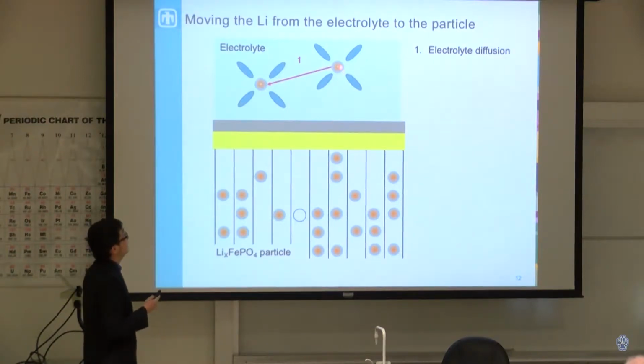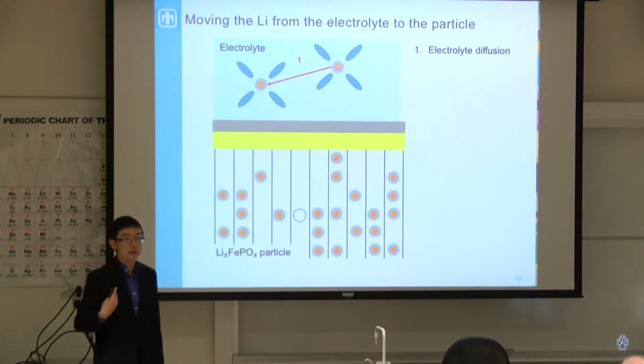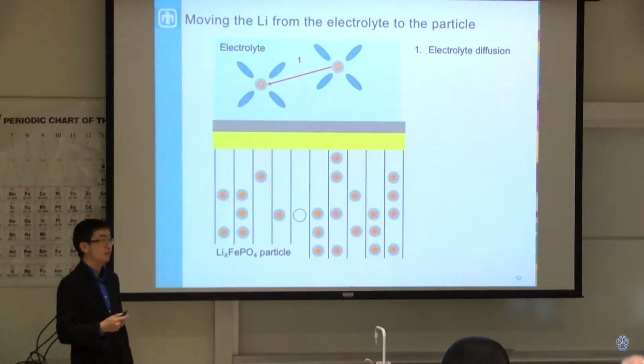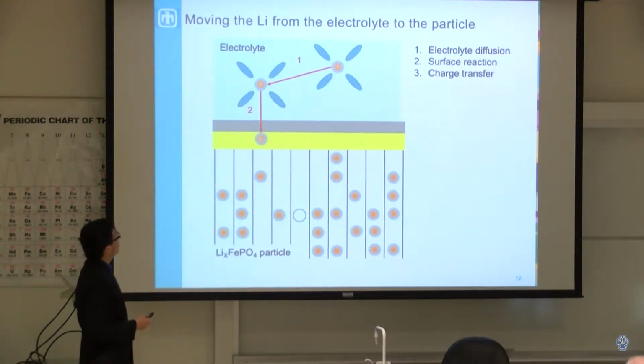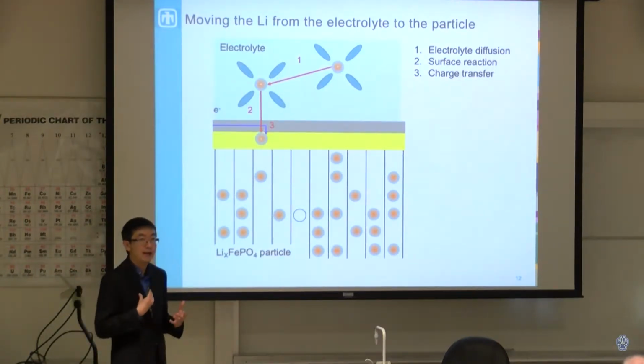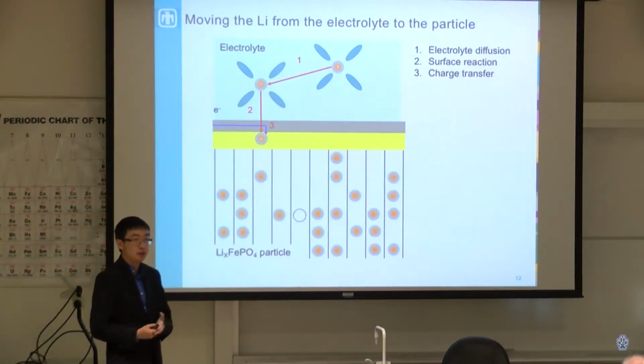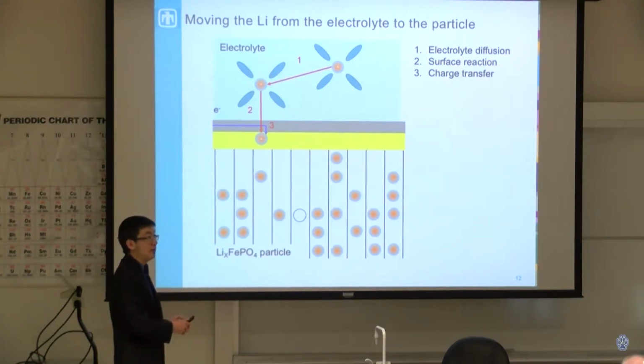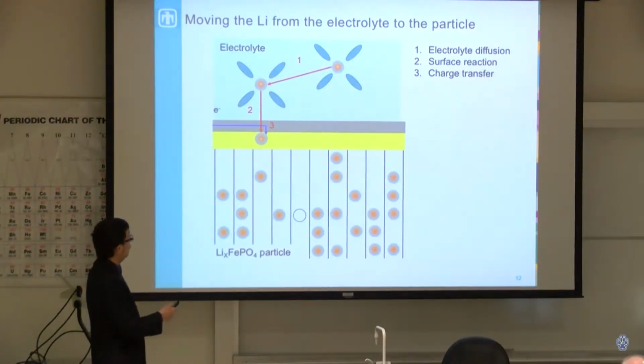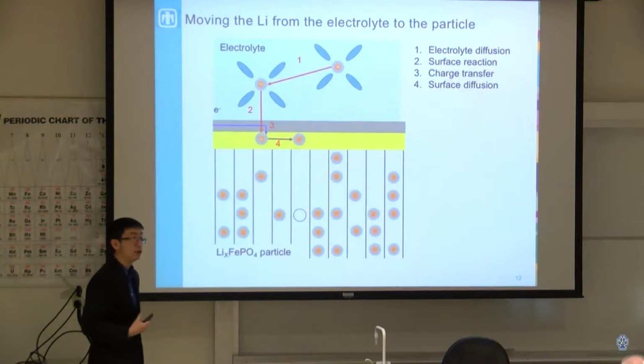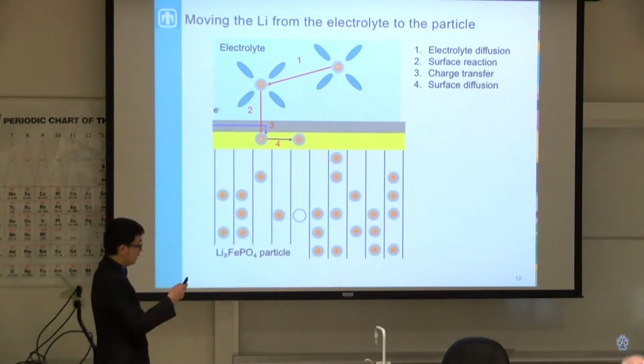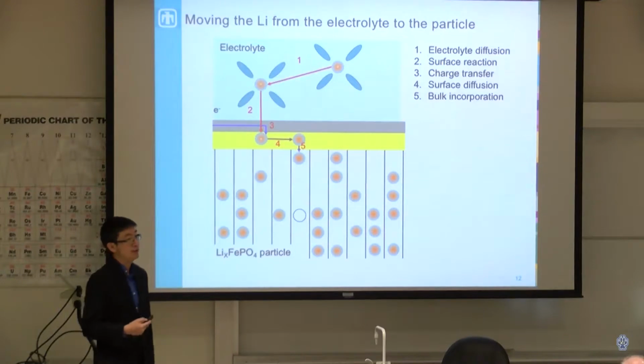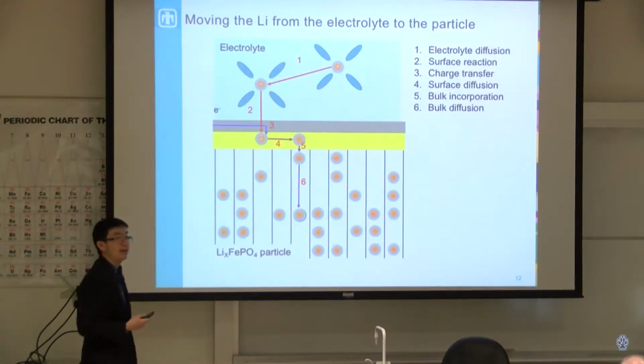The first is that lithium must diffuse in the electrolyte. These are liquid electrolytes, so ions can diffuse very readily in them. What must happen next is that lithium must go into the particle, from outside the particle into the particle, and simultaneously accept an electron. When it accepts this electron, this is when charge transfer happens. So it goes from a positively charged lithium ion to an elementally neutral lithium. Once that happens, it tends to go around on the surfaces before incorporating into the bulk. And once it's in the bulk, it can later diffuse inside of the particle.